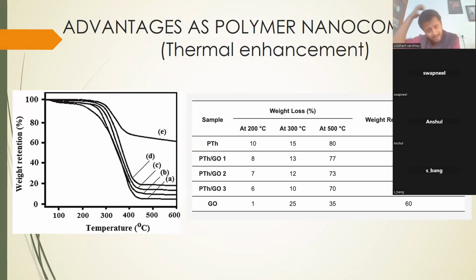Then the thermal enhancement, as you can see. This graph is called a TGA, thermogravimetric analysis. All this graph is telling you is that by adding a very small percentage of graphene oxide, the thermal resistance increases. From A to E, the virgin polymer is A, and it is shifting up and towards the right side. That means the thermal resistance is increasing, and just by adding 0.1 or maybe a maximum of 1 weight percent of graphene, you can increase thermal stability by up to 50 degrees Celsius.